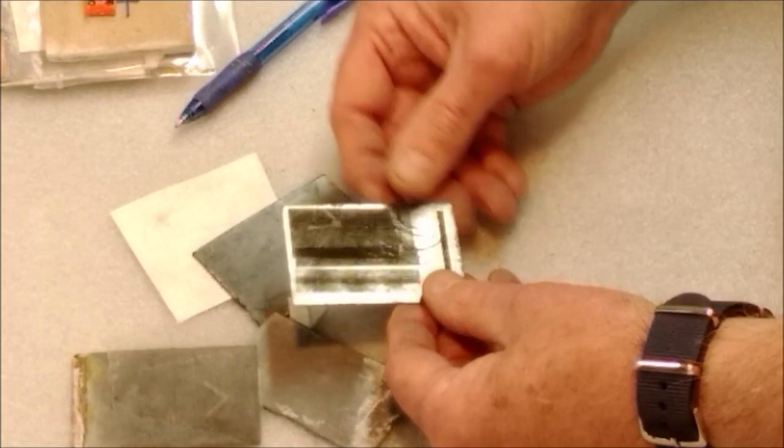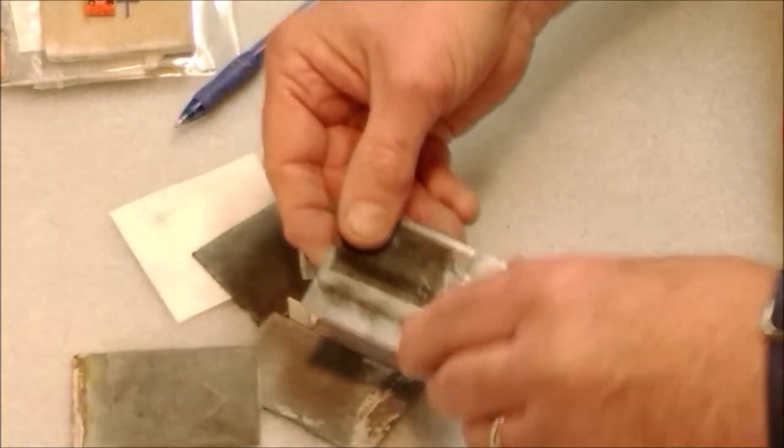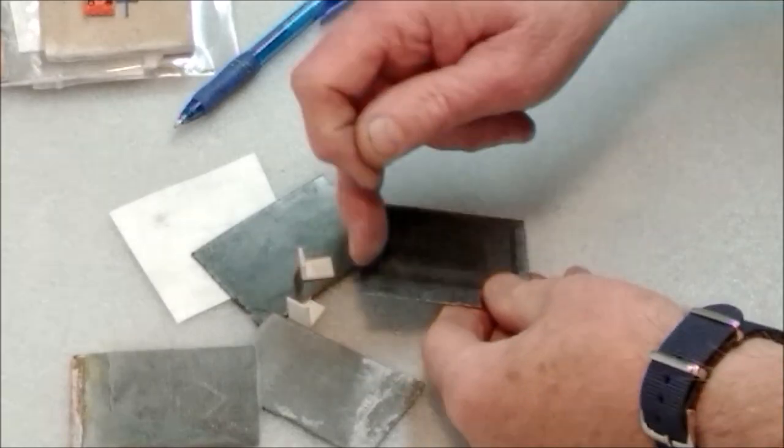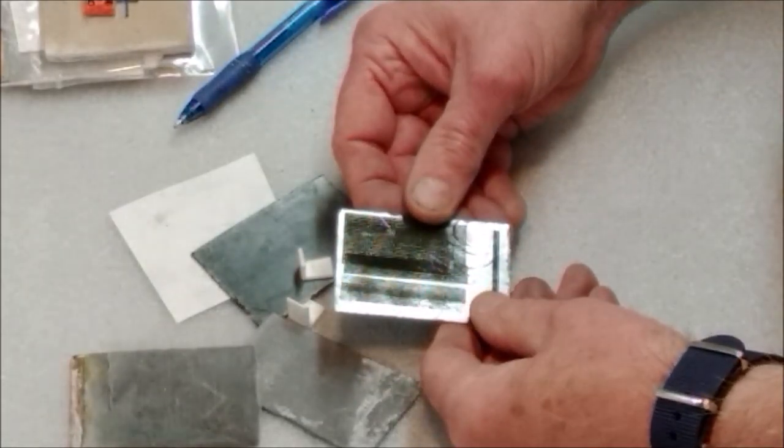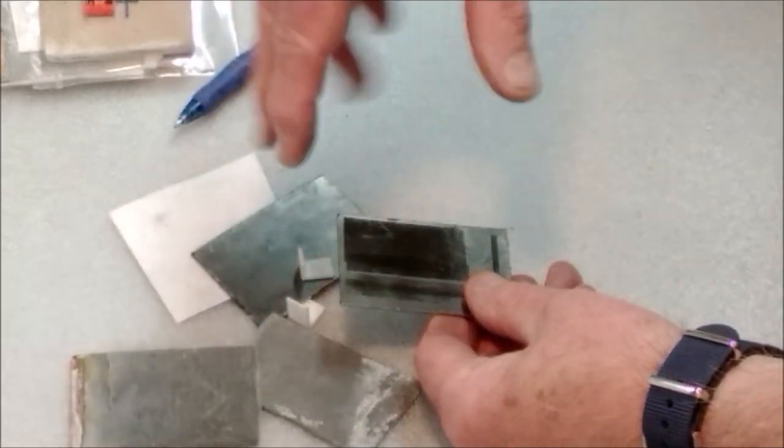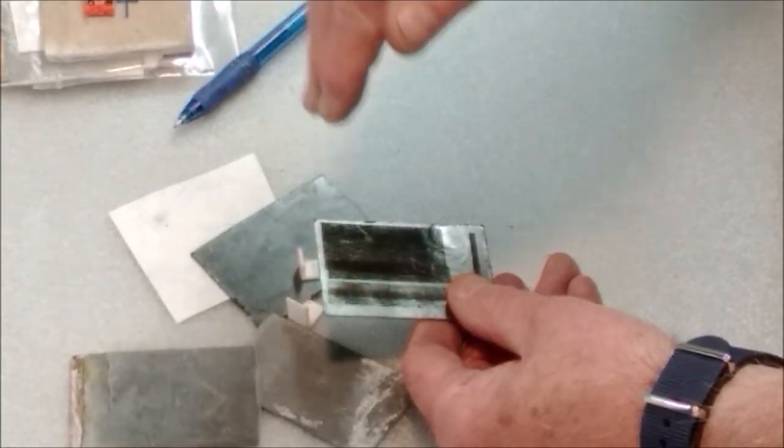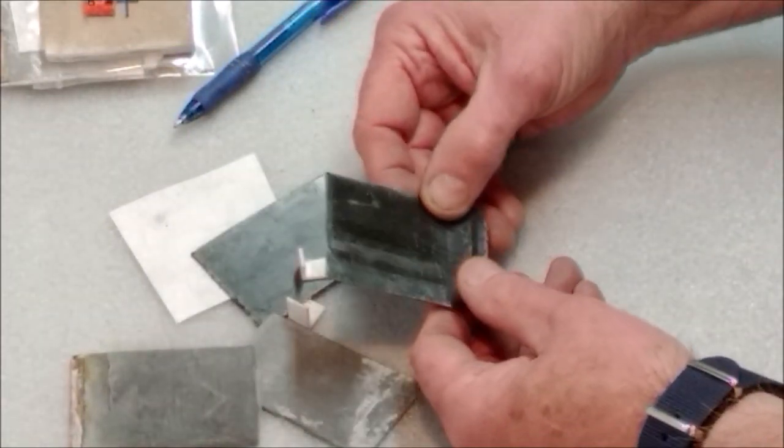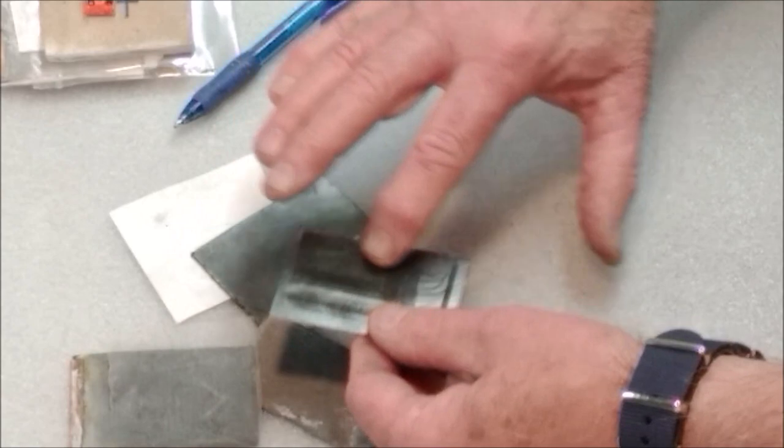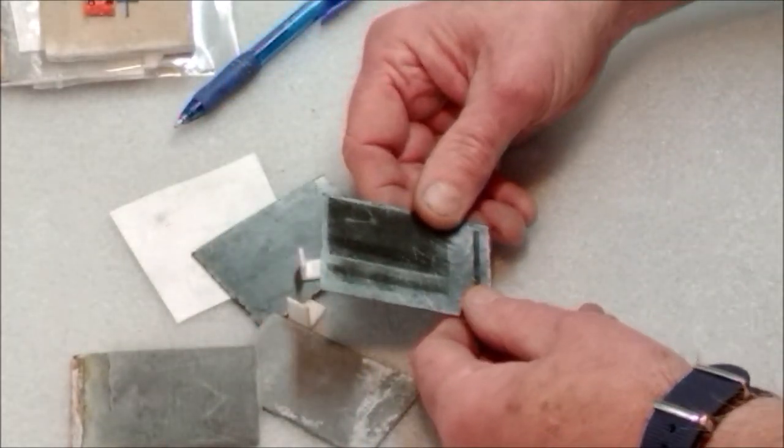If I turned the power of the laser up very high, I would actually cut all the way through the sheet. So through a number of experiments and some trial and error and playing with the scan rate and the amount of power, we were able to create just the right amount of laser erosion or exfoliation on the surface. I'll insert here some photos where you can get a close-up view of that surface. Here's a sample here, one of my test samples where we use various powers and scan rates. You can see some fuzzy areas, some scanned areas on this sheet. This was all done by the laser.